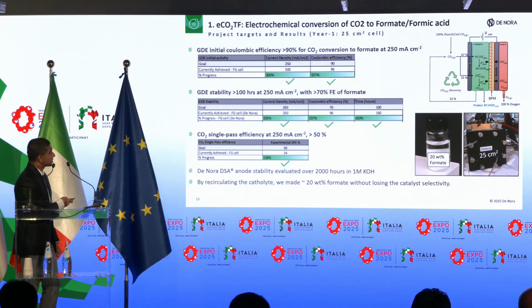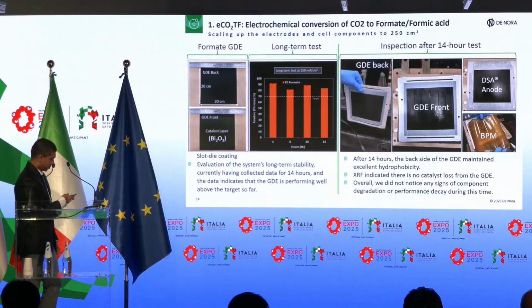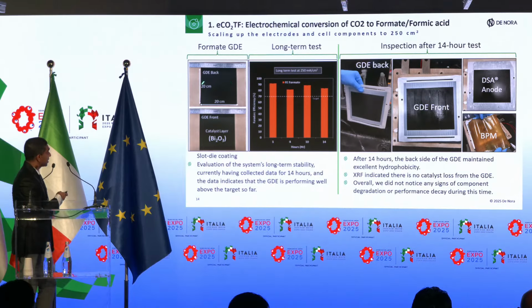So this slide basically summarizes everything I just discussed. So I'm going to move to the next phase of this project. Here, as I mentioned, we scaled up the same electrode components to 250 square centimeter size. This is the back side of the electrode, and this is the front side, where we have a catalyst layer, which is bismuth oxide. We deposit this catalyst layer using a slot die method, which can result in very uniform coating.